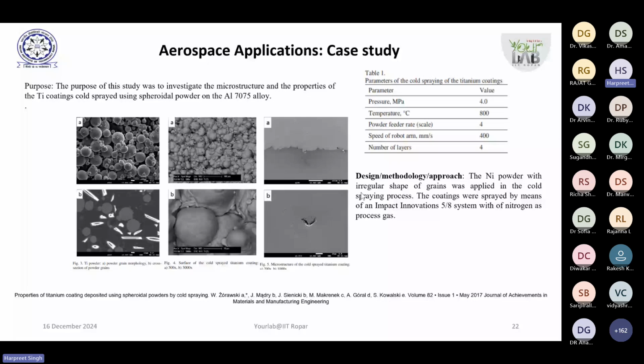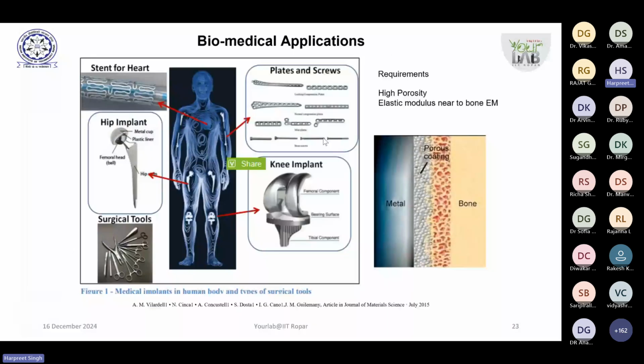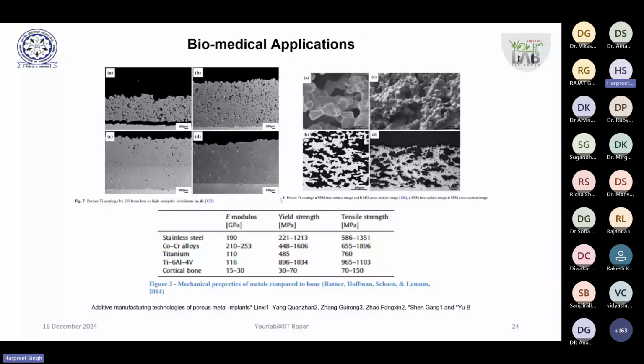Another material which is very favorable to aerospace is titanium based coatings on aluminum based alloys, and you can see very nice coatings have been developed, again, not our work but from literature. See how beautifully these coatings are being made. Biomedical applications, as I told you, have a lot of market, and so many types of coating techniques have been used. So is the case with cold spray also. People are trying. For example, this is a porous titanium coating by cold spray.